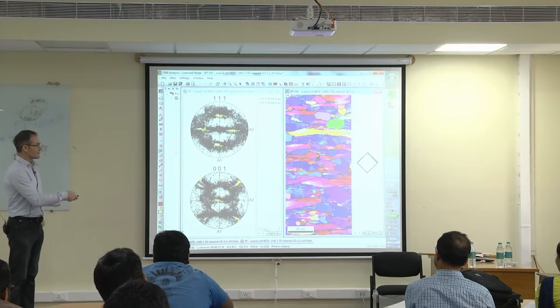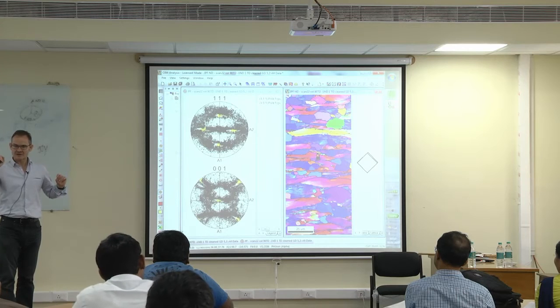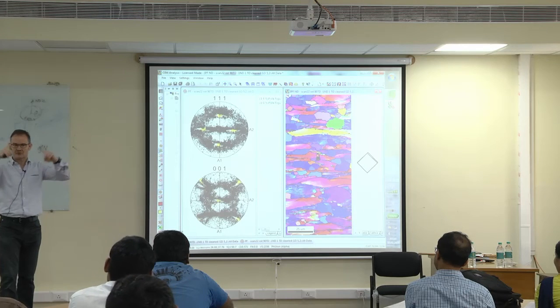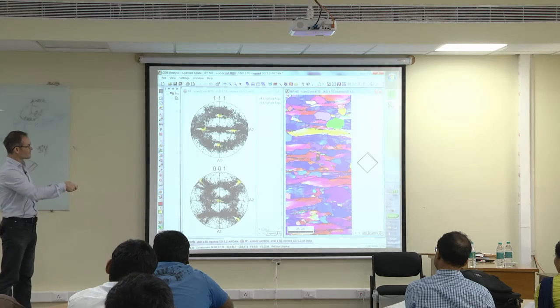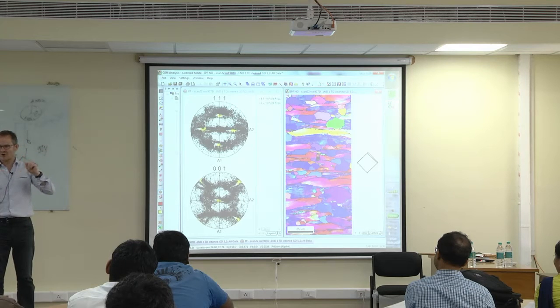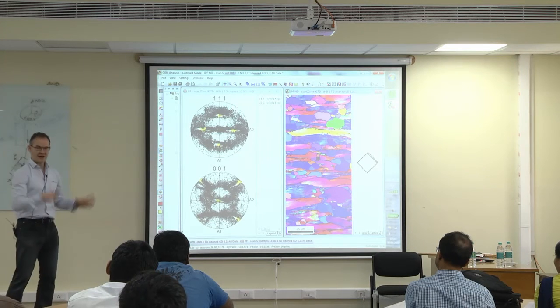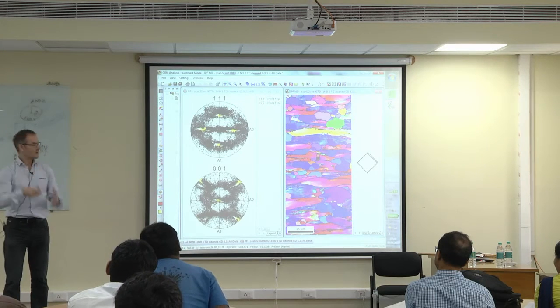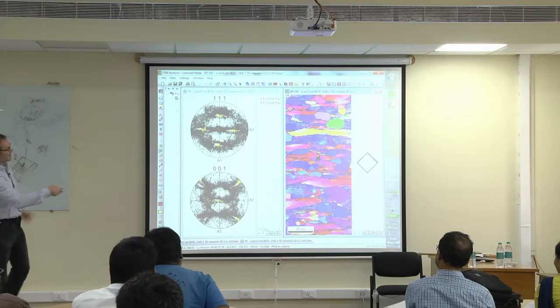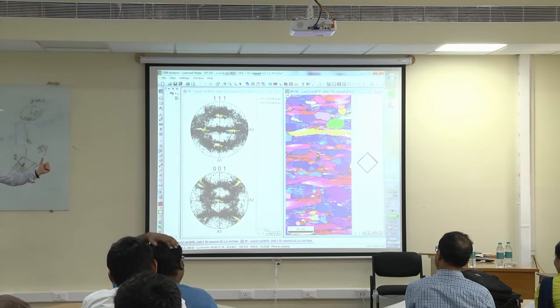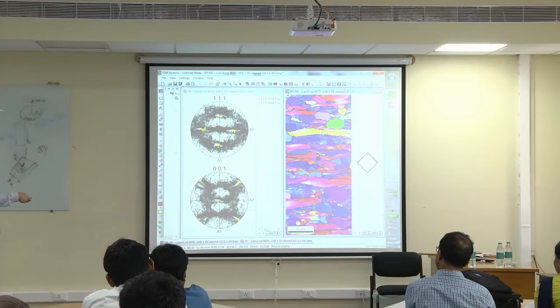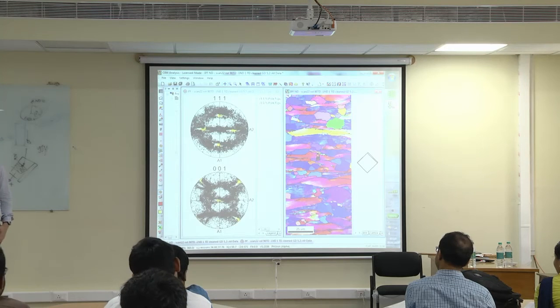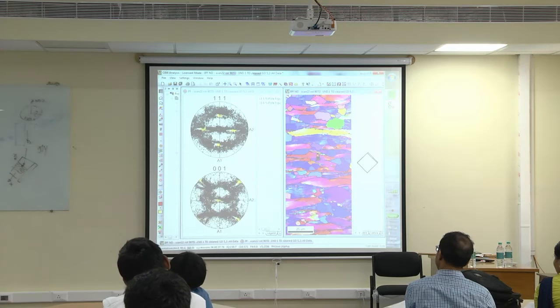And this is actually the reason the blue grains, which are 1-1-1 oriented grains, have a dislocation structure which is rather mobile. So when you do this rolling here, these dislocations can arrange and form subgrain structures. The red grains have dislocation structures which are entangling each other and which are not very mobile. Therefore the red grains stay in their continuous orientation gradient. And this will later lead to the fact that this one can nucleate. It nucleates new grains, while the red grains do not nucleate new grains. Yeah? And this is already visible a little bit in this structure, yeah?